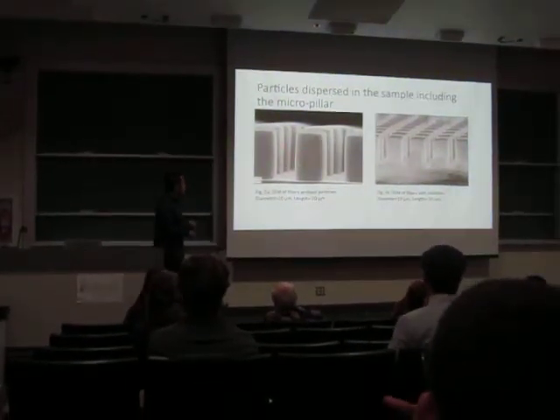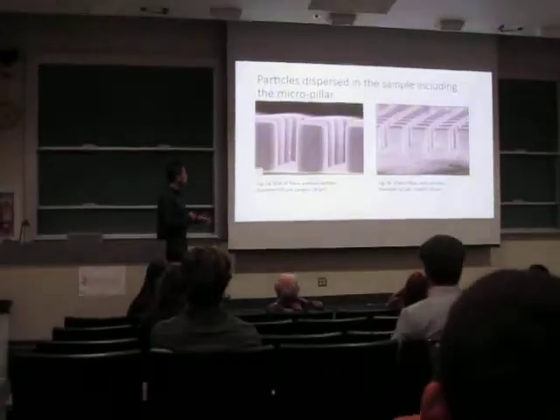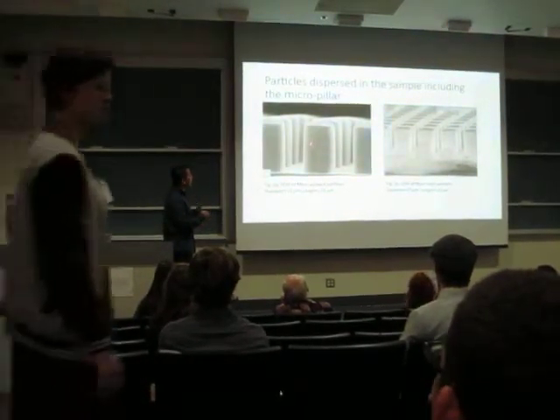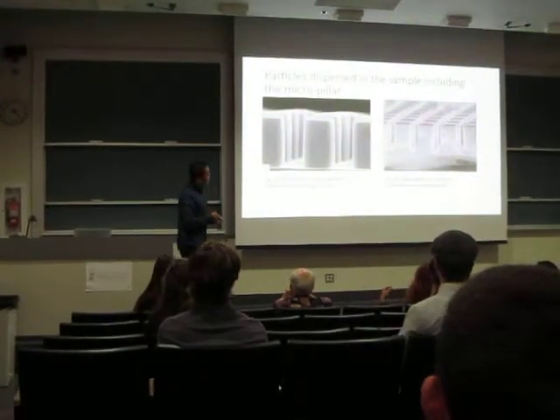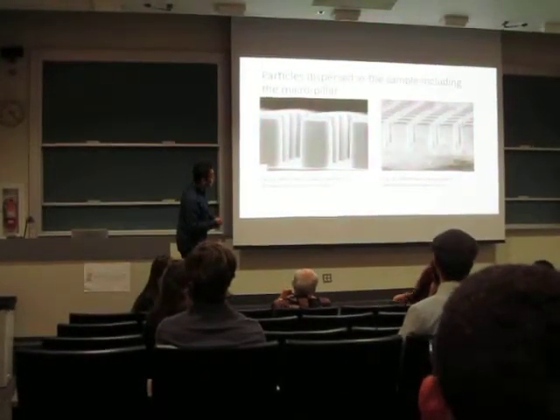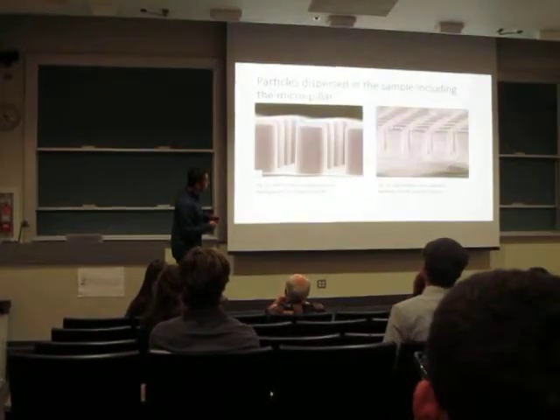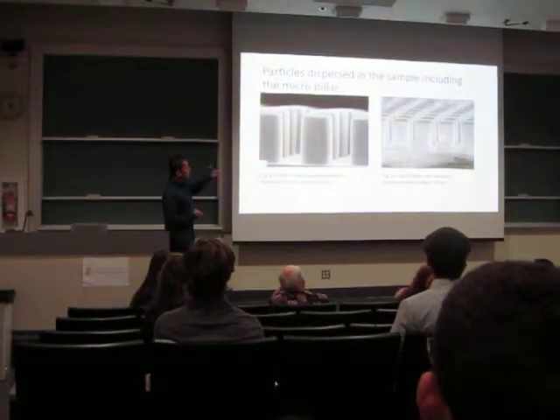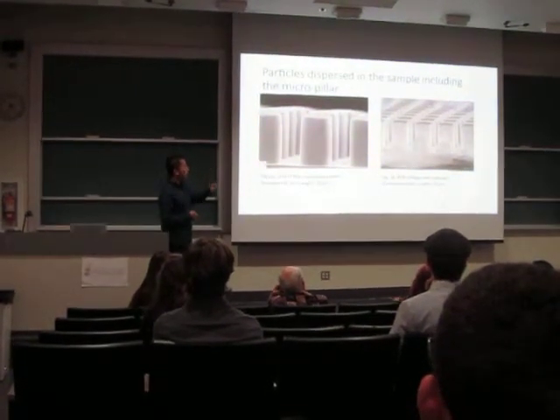There are two types of samples. The first one is pillars without any particles, so we just play with the curing agent. This is the SEM picture of the perfect pillars. And also we have the one with particles. As you can see, there are some particles right here, also in the pillars. This is the SEM image of PDMS mixed with particles.